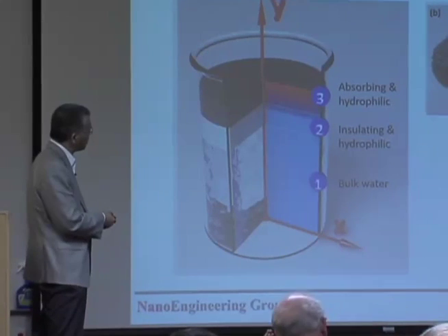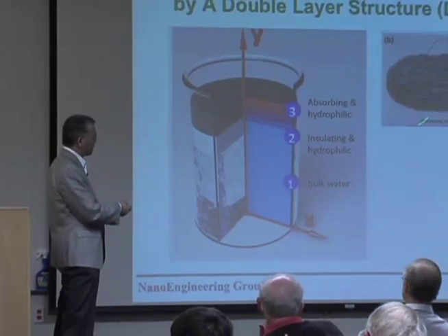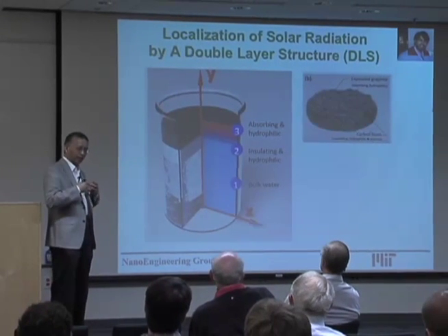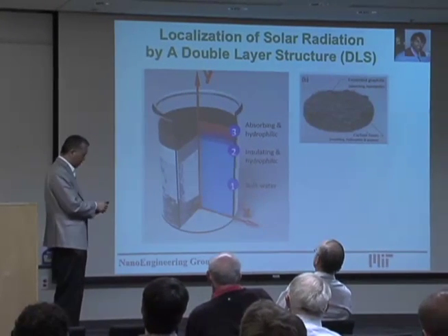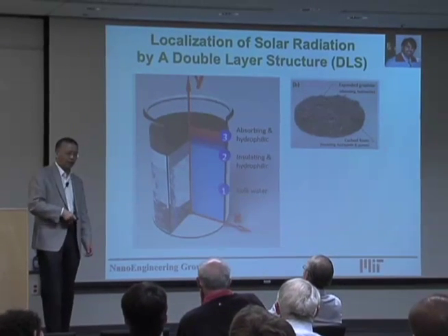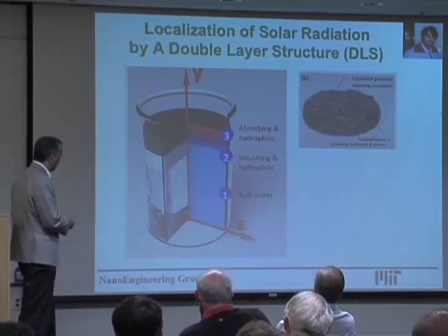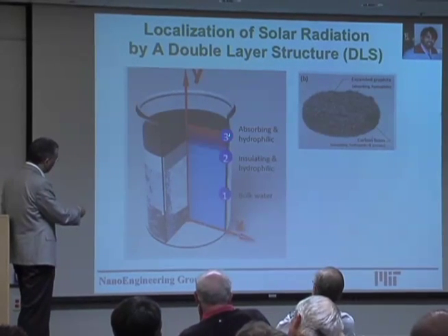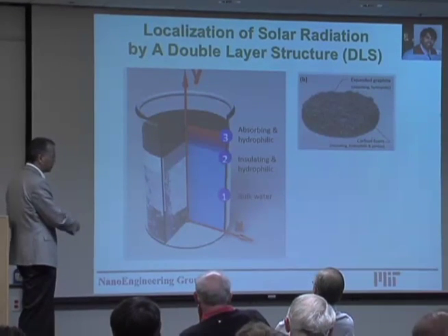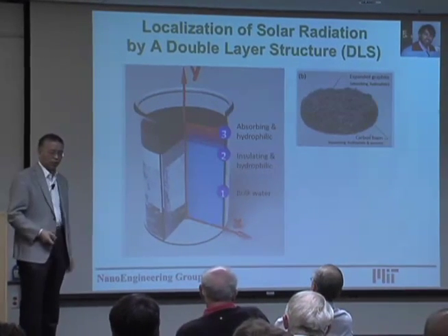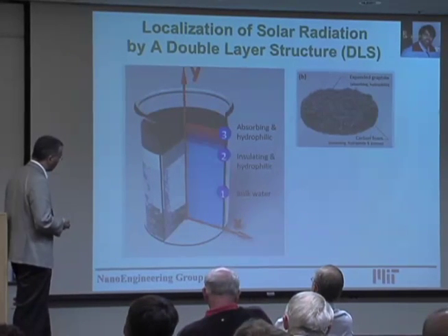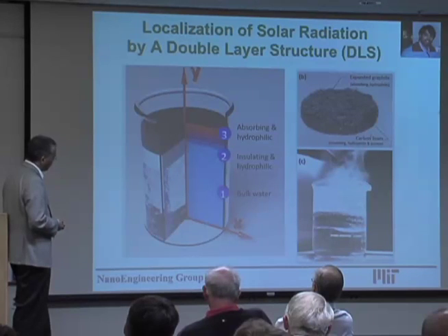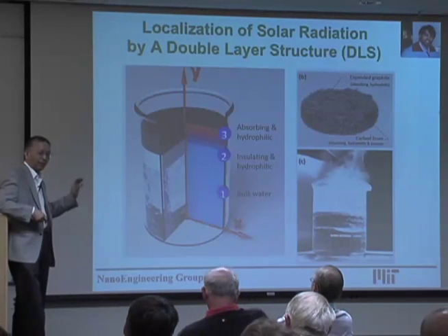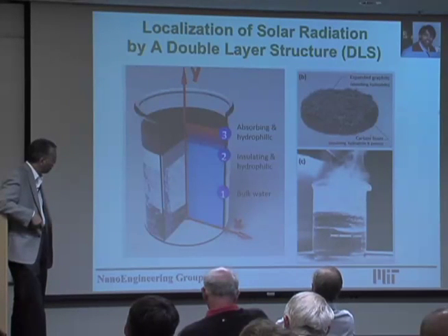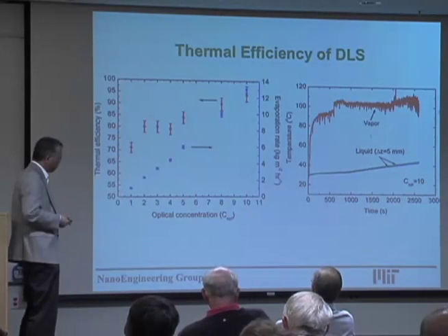This is in fact pretty simple. It's graphite flakes on carbon foam. Water is hydrophilic, so water is actually sucked into the top surface layer. With that, the heat is absorbed in this region, rather than normally, when we want to do evaporation and shine solar light, it is absorbed through the whole volume. So it's quite effective. I'm going to show you some data, but you can tell just from the vapor that it's pretty effective.